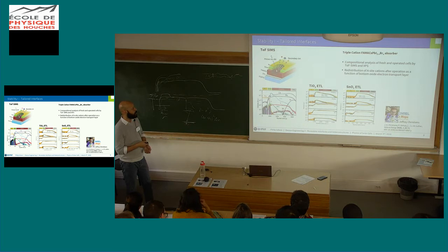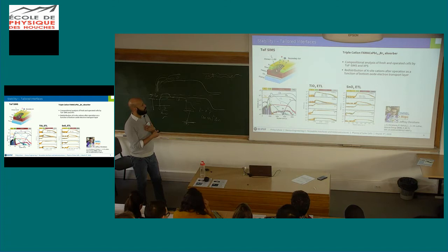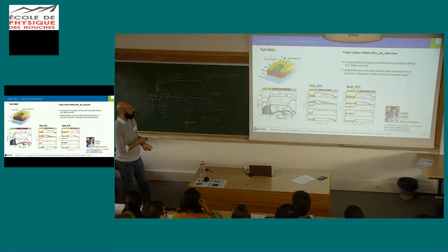What I show you here are time of flight secondary ion mass spectrometry curves. So these are depth profiles. You dig with your primary ion beam through your layer, and you collect the secondary ions and thus reconstruct what sort of materials were in the layer that you are currently digging out. This gives you this convoluted graph over here where you have the sputter time that is not completely equivalent, but corresponding to the depth that you are in your sample, starting off with the gold, and then you see all the different components from the perovskite solar cell.